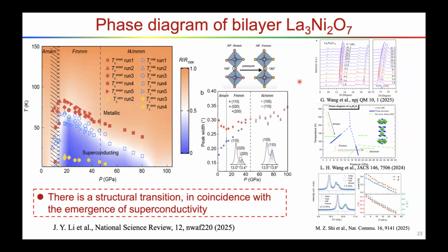Later on, our collaborators measured the sample with synchrotron diffraction. They claim the tetragonal structure corresponds to the superconducting state. And for the work from Jinguang Cheng's group, they also claim there's an orthorhombic to tetragonal structure transition at high pressure. But